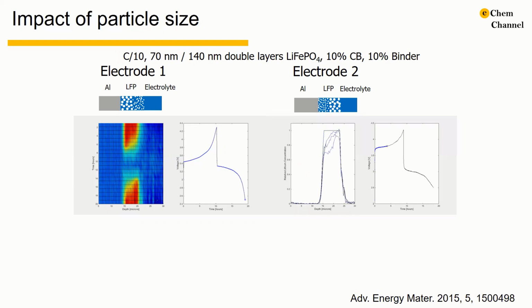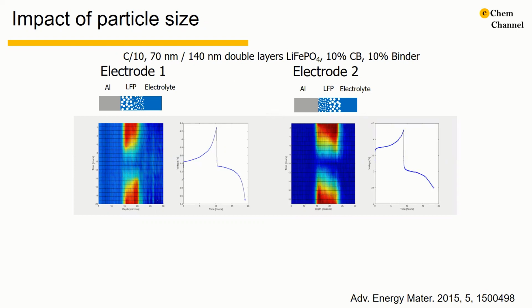For the second situation, the experiment is performed again on the electrode 2. The result shows that the smaller particle close to the current collector loses lithium faster when voltage increases and gains the lithium faster when voltage decreases. So no matter where the small particles are, they always charge and discharge faster than the larger particles.